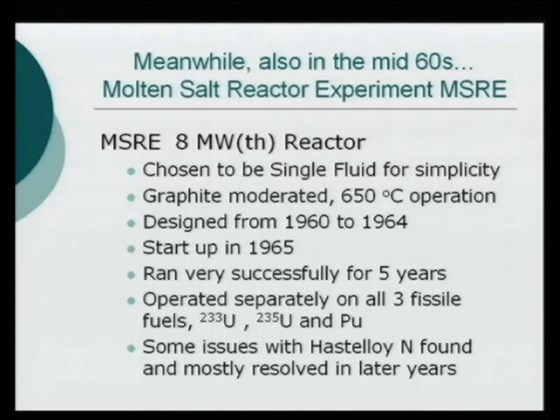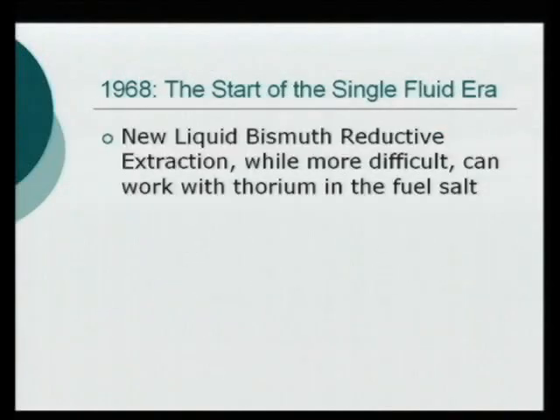They found some issues with that Hastelloy, that high nickel alloy metal. One with a certain fission product that was getting into the grain boundaries, and another with neutrons that can make helium inside the metal, and that helium gets to grain boundaries and gives you problems. But later on, they worked with alloys and not 100%, but mostly resolved those issues, and we could definitely do more now. Now, 1968 is what I call the start of the single fluid era.